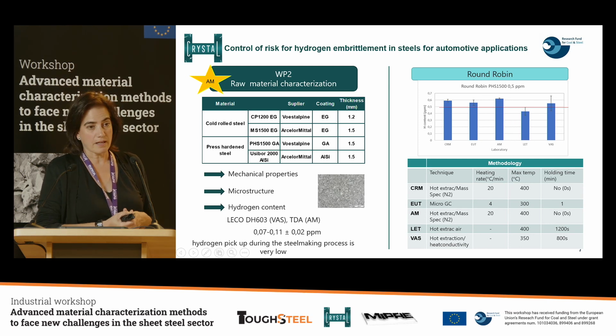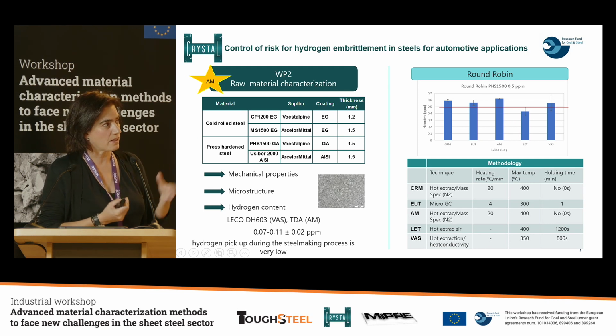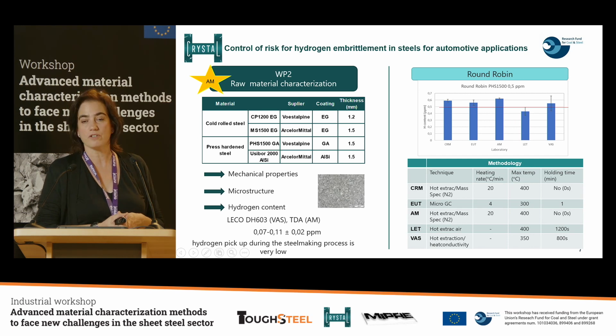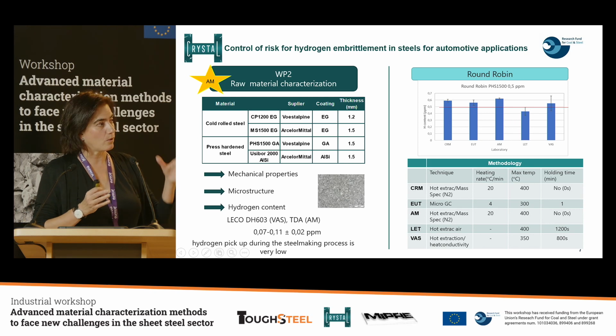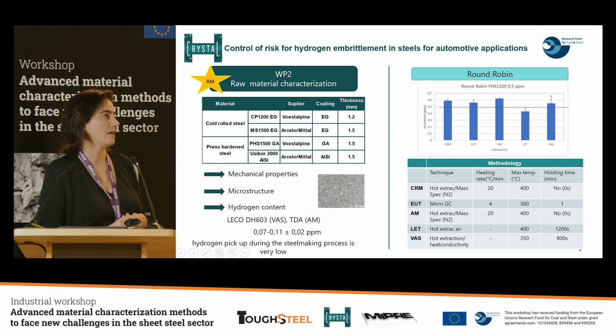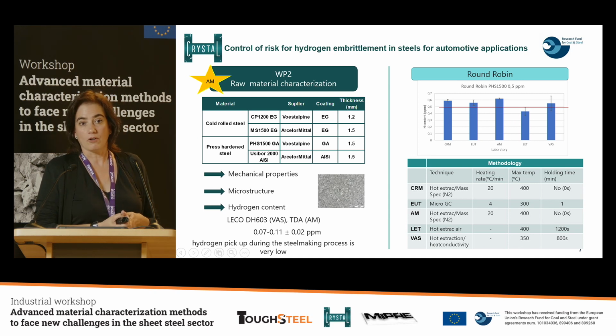So CRM was responsible for charging, in this case, a PHS 1500 with 0.5 ppm of hydrogen, and then we sent it to all the partners. And we measured what the content of the hydrogen was. And as you can see in the graph, we considered that all the hydrogen measurements in the consortium were acceptable.